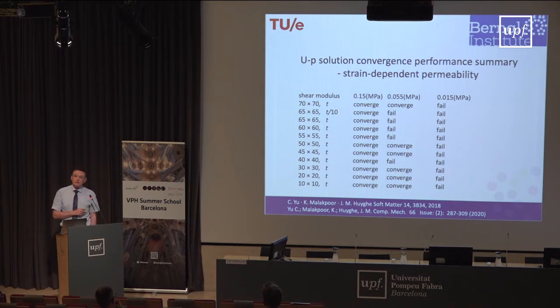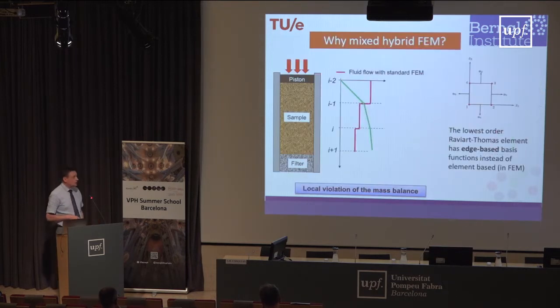Now, the trouble is that you cannot do something about it inside Abaqus or inside ANSYS or whatever package, because you have to be able to look inside. And so what we did, we first analyzed very carefully why the problem comes up. And what we found actually is that one of the key issues here is what is called local violation of mass balance. Local violation of mass balance.